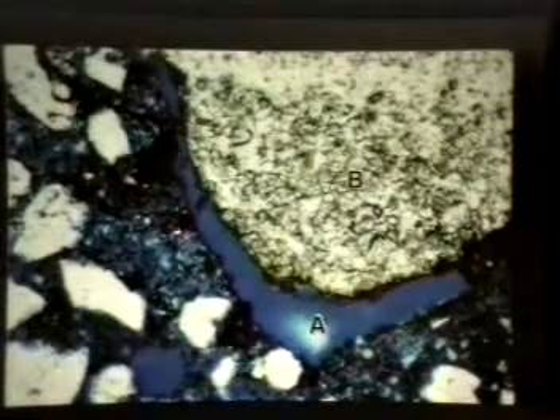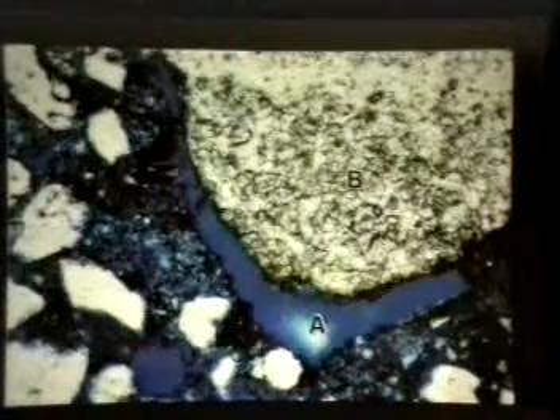When you look at the same concrete below, let's say 3 or 4 inches below, we are talking about concrete slabs, you will see that the paste has been affected. All the lime has been leached out, and the paste porosity has increased. This is all leaching. This originally was occupied by some paste constituents but has leached out. So this is what vapor transmission can do to the concrete.